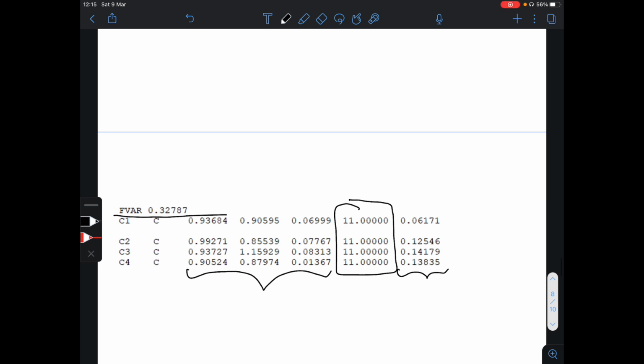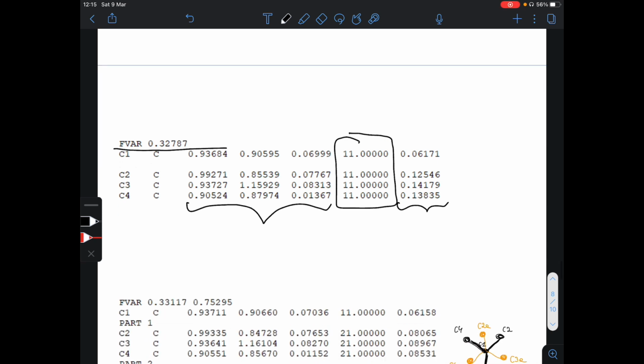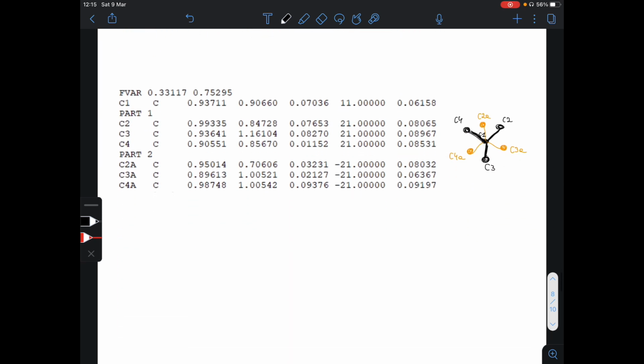So after we split the atoms into two parts, our ins file would look like that. So we have the first atom that is not involved in disorder, so it's beyond part 1 and part 2, it's in part 0. Then we have atoms in part 1. Then we have atoms in part 2. And I forgot to write it down. Whenever we finish part 2, we should always say part 0 to distinguish between the atoms that we involve in part 2 and all the other atoms that can be beyond these atoms in the ins file.